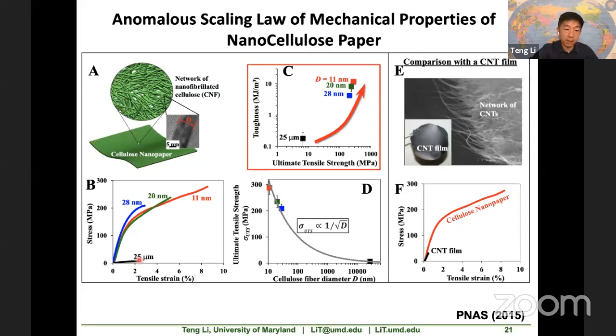Now, if you break down the diameter of the cellulose fiber 1,000 times to 28 nanometer, and you make this cellulose nanopaper, you can see that the ductility increased modestly. However, the strength increased substantially, to more than 200 megapascal. You further decrease the diameter of the cellulose nanofiber to 20 nanometer. You see that it becomes more ductile and even stronger. The thinnest one we achieved is 11 nanometer. It can be stretched more than 8%, reaching a strength around 260 to 270 megapascal.